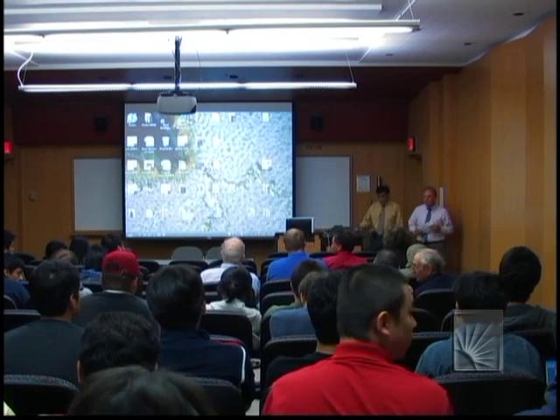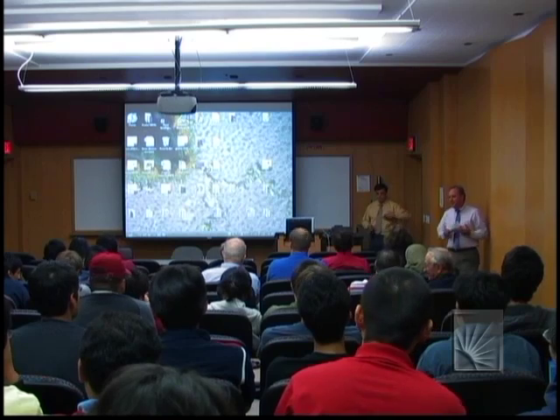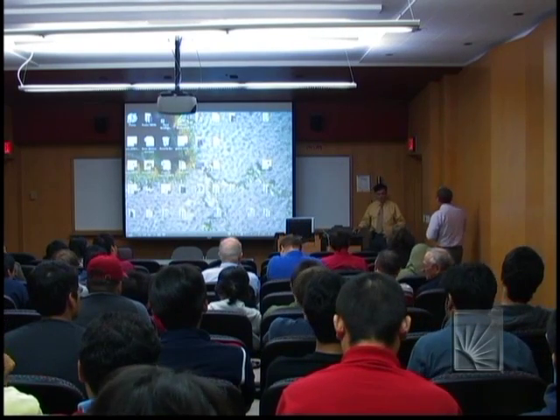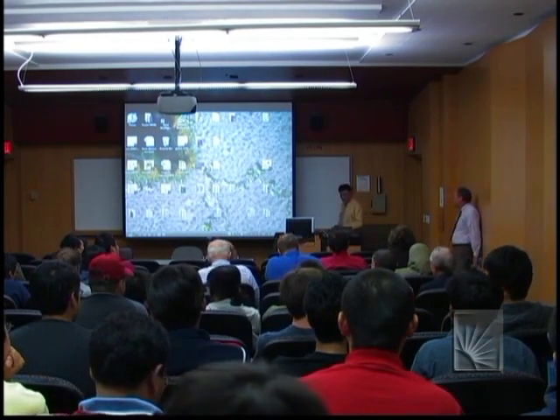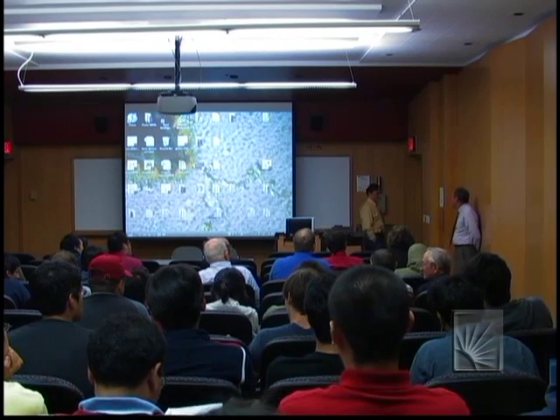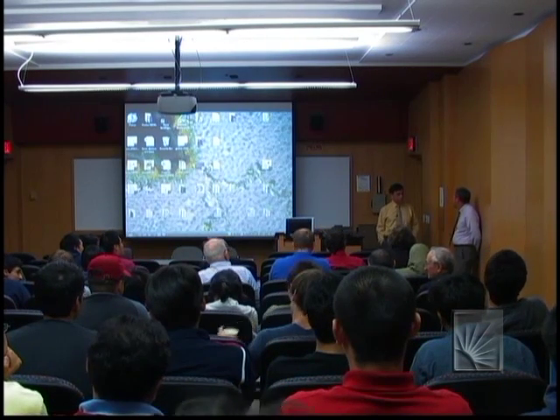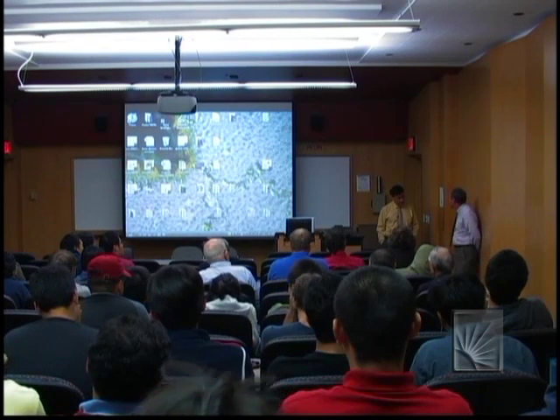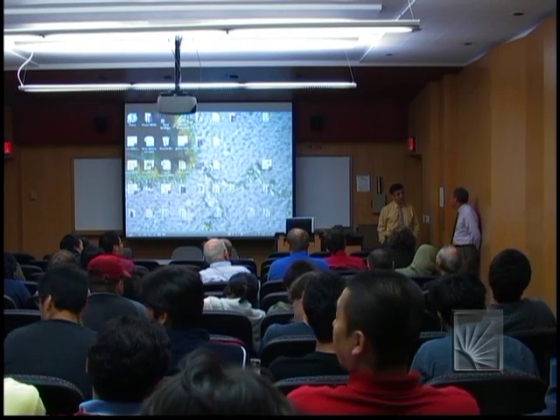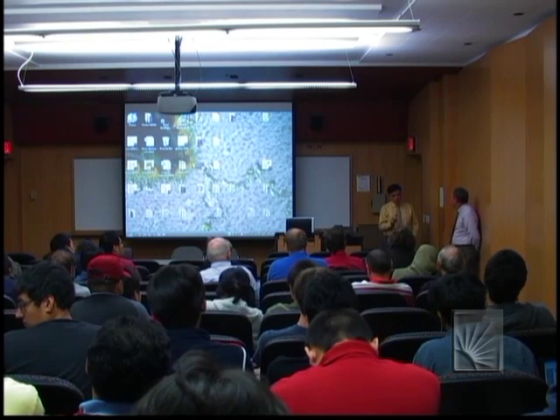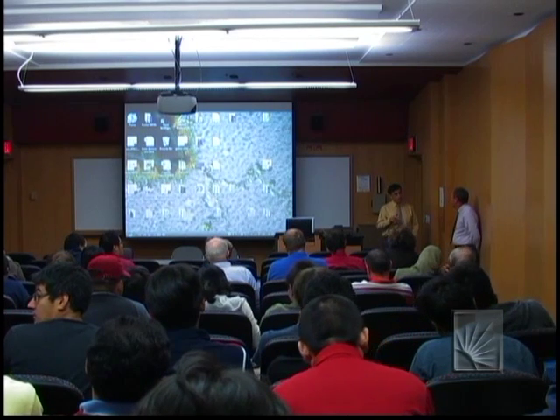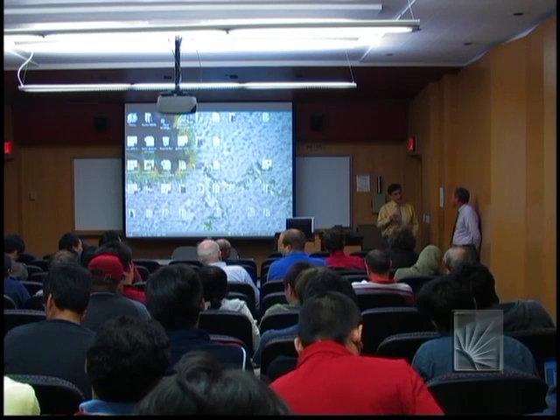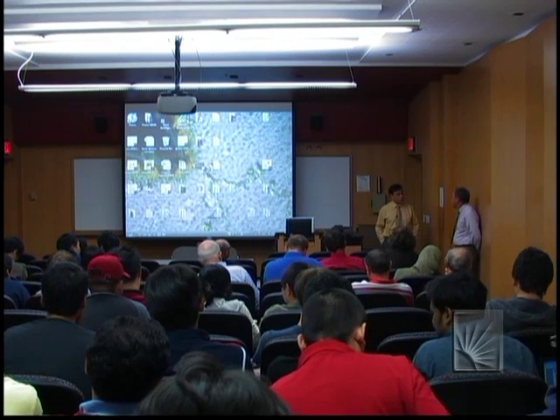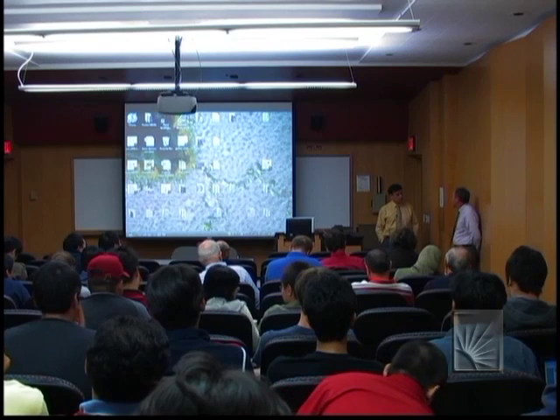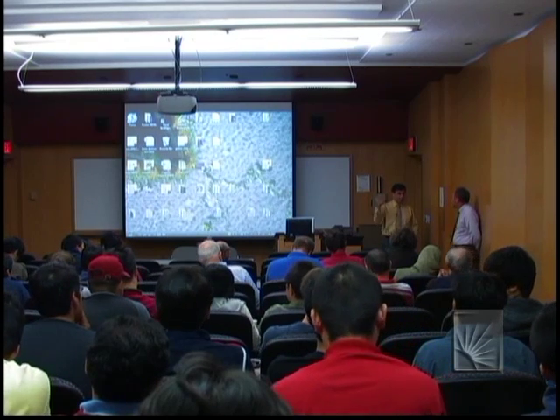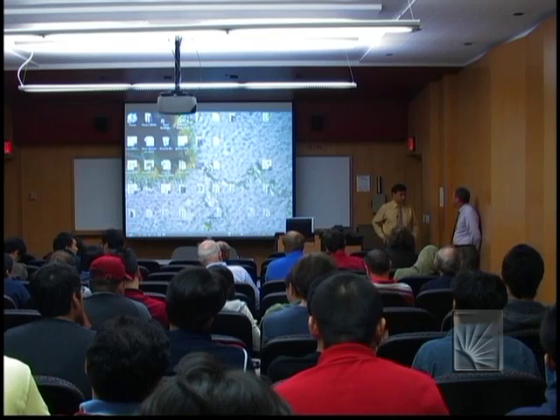Okay, we're now ready for questions. I'm going to ask the first one then. Going back to the carbon nanotubes. One of your early slides showed that carbon nanotubes have a band gap energy, and it goes as the reciprocal of the diameter. So the smaller they are, the semiconducting version of them becomes higher band gap. It usually saturates around 1.2, 1.3 eV. So in the limit of making them 0, the band gap becoming infinity, it's not really physical. It doesn't have a physical meaning.